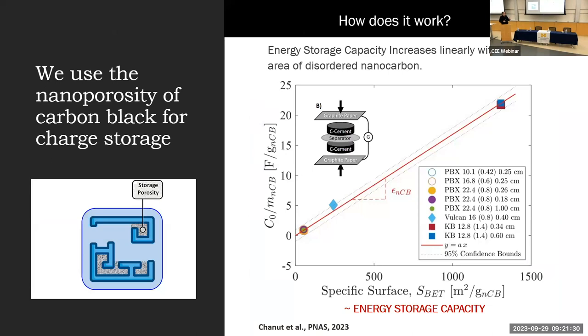And here is the key point, one of the key scaling relationships: this energy storage capacity, expressed by this quantity, capacitance, scales with the specific surface of the carbon black linearly. These are all tests with different thicknesses, different water-cement ratios, different types of carbon black. And you see here that you are able to scale this merely by choosing the specific surface inside the material, independent of the volume, meaning you have an intensive quantity identified with which you can work in order to scale the material.